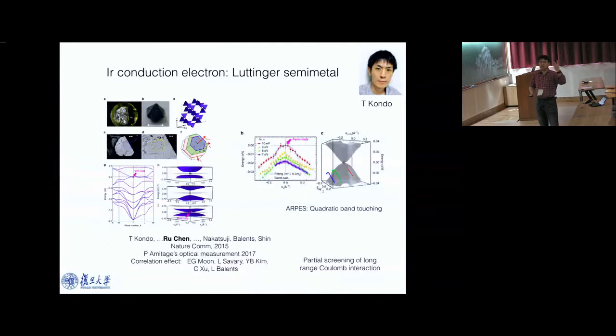So each band is twofold degenerate, and this conduction band and valence band touch at the gamma point, and this band touching at the gamma point has a fourfold degeneracy. Right? This fourfold degeneracy corresponds to the gamma 8 representation of the cubic group. So this band touching, as a result, is protected by the cubic crystalline symmetry.